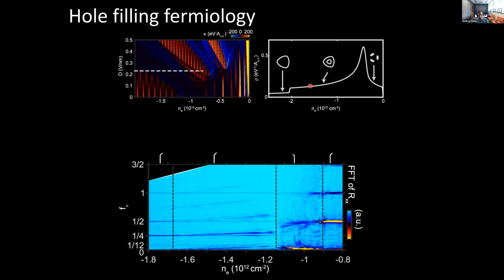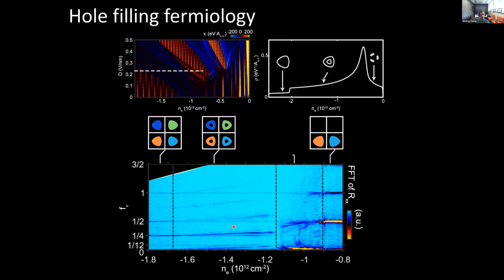And that's a tunable knob. So we can try to work out this fermiology, and we find that at high density, as I showed you before, you have 4 simple Fermi surfaces. Across a cut here, you can see that there are regions where you have 2 simple Fermi surfaces, so something that has broken the spin or the valley degeneracy. As it turns out, that's already more complicated here than on the electron side. You have regions of annular Fermi surfaces, and then you have regions which we'll call partially isospin polarized, where you have a lot of spectral weight in these quantum oscillations, somewhere a little smaller than 1/2. You have a fair amount just above 0, and presumably these sum to 1/2. So you have maybe 2 large and 2 small Fermi surfaces, but it's a little hard to tell because the quantum oscillations there are quite complicated. They're not as sharp or well-defined as they are in some of these other phases.